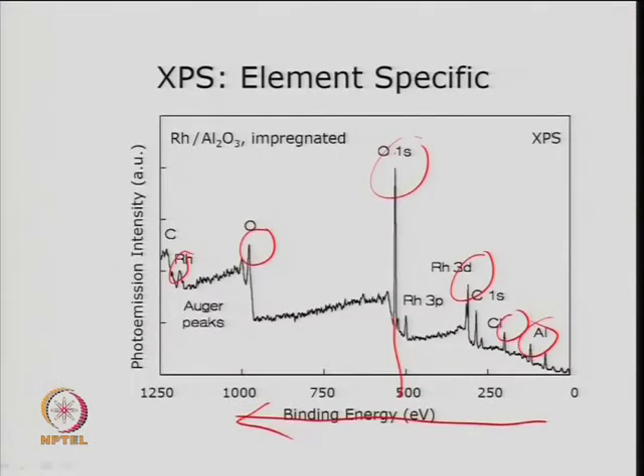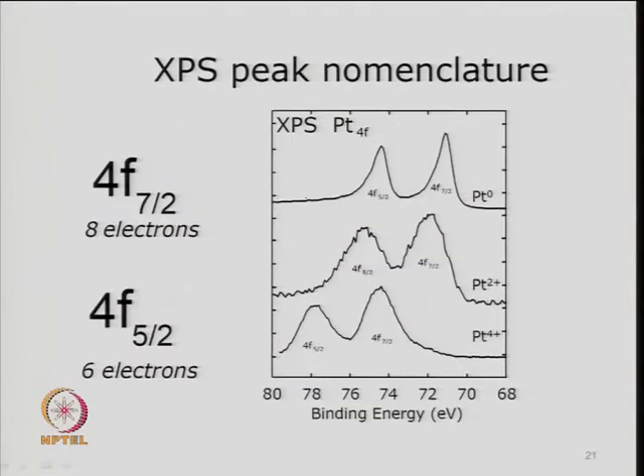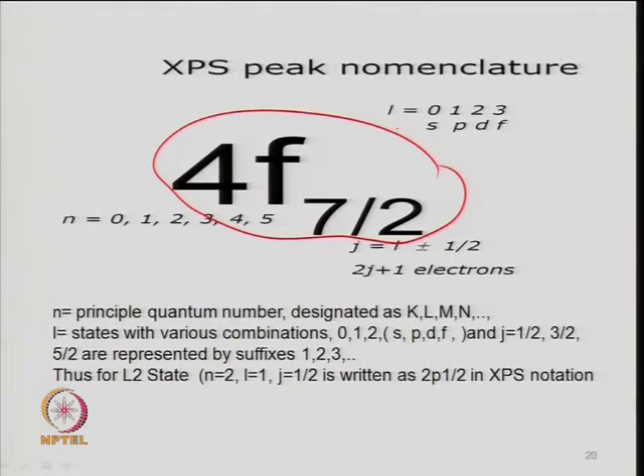The notation used — such as 3d, 1s — can also appear as 4f 7/2 or similar. Most of the time we report it like this: for platinum, 4f 5/2 and 4f 7/2, representing platinum 0, platinum 2+, and platinum 4+. Different oxidation states have different binding energies — for example, roughly 78, 74, 73, or 72 eV, depending on the oxidation state.